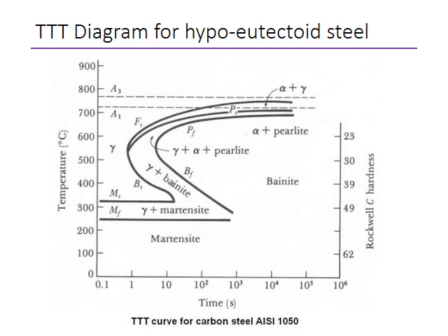Now, if the quenching is more severe and you pass this temperature, now we can see that there is no longer primary ferrite appearing here. So primary ferrite will exist only for quenchings which are lower than this undercooling value.